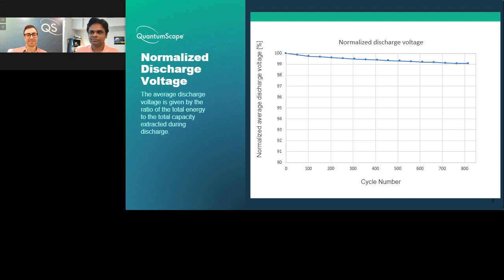So we don't expect to see voltage fade out of our cathode active material because we're using a nickel-rich material. But if there is a lot of excessive impedance growth in the cell or resistance that crops up in the cell, then that will also manifest itself as decay in voltage. And so what you're seeing is that all of these in concert result in only 1% voltage fade throughout this test.